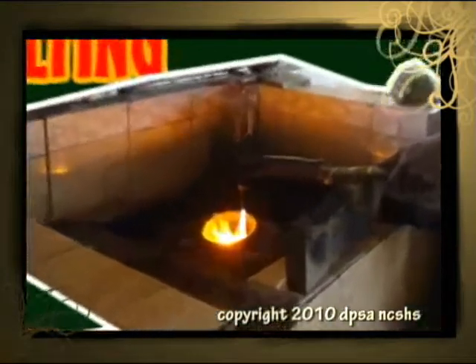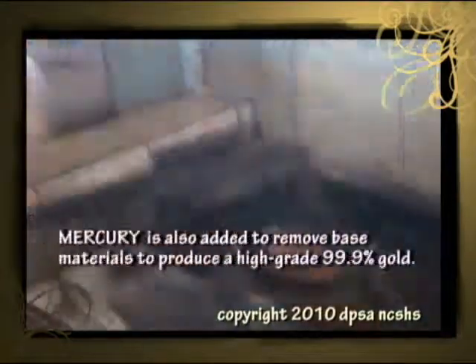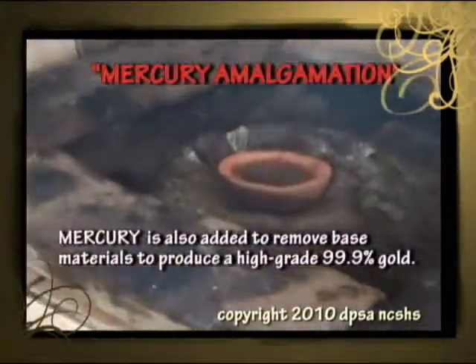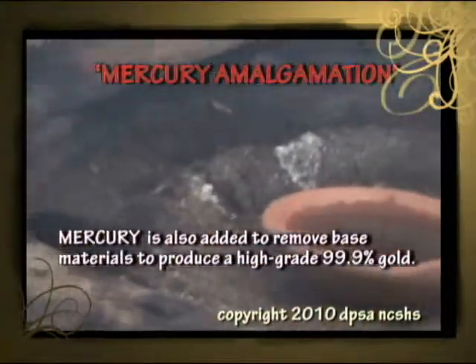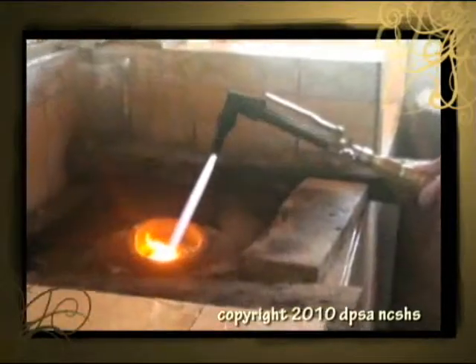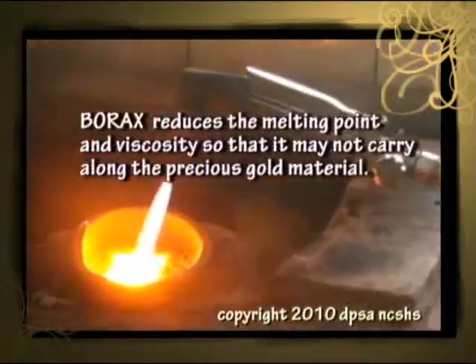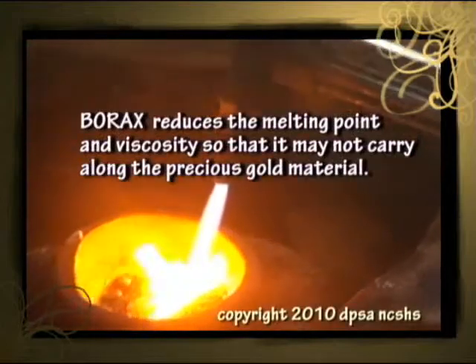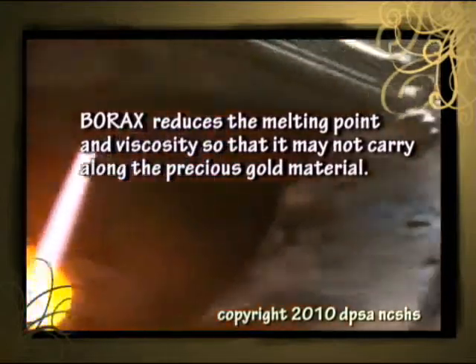Smelting is another process by which the gold precipitate is further refined. Mercury amalgamation is under smelting process, where mercury is added to remove base materials to produce high-grade 99.9% gold. Borax is added to reduce the melting point and viscosity so that it may not carry along the precious gold material.